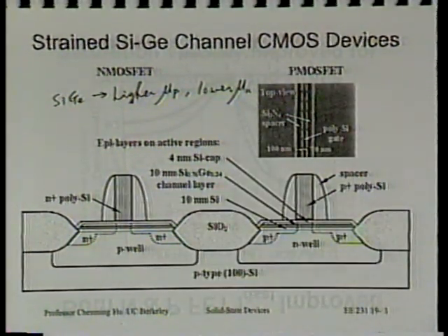If the silicon germanium becomes very thick, a few thousand angstrom thick, then the strain is relieved. Okay? So now on top of that, people have grown a layer of silicon, and that becomes the material for the N-channel transistor. Now that thin layer of silicon becomes strained because it is grown on unstrained silicon germanium. Do you see how this goes?